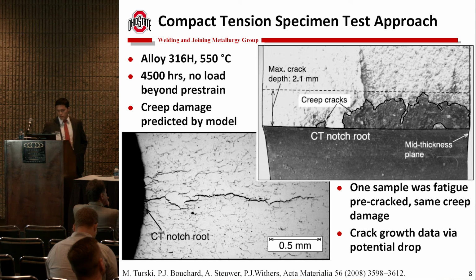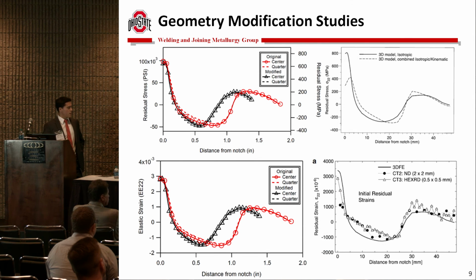And so what I wanted to do was extend this approach to much thinner samples, mainly because I had a whole bunch of half-inch thick plate. And so my approach there was to start by making an Abaqus model, just a simple elastic plastic model, and lining it up with Turski's model because I knew he had validated that his model was accurate. So I did that, and those are the red lines, and then it was real easy to start changing the geometry, and so I made the sample smaller this way, and I reduced the thickness to 40% of the original thickness, and was still able to have a pretty similar stress and strain profile immediately behind the notch.